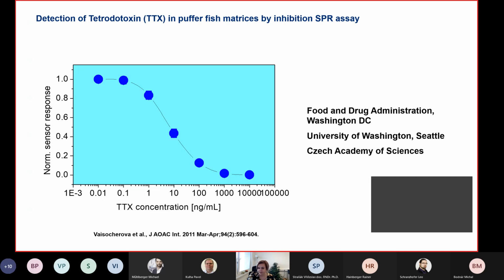Here is some preliminary data from our experience. This is detection of tetrodotoxin, which we did in the past in collaboration with FDA and the University of Washington in Seattle. We developed an inhibition assay for detection of tetrodotoxin and monitored it by the SPR technique. We also developed an SPR biosensor for detection of bacterial pathogens in food samples. We used a three-step assay for amplification. We used a secondary antibody step and then binding of functionalized gold nanoparticles. And as a substrate, we used a carboxybetaine-based antifouling zwitterionic substrate, and also another modification of this substrate as a copolymer. And we got very interesting results.